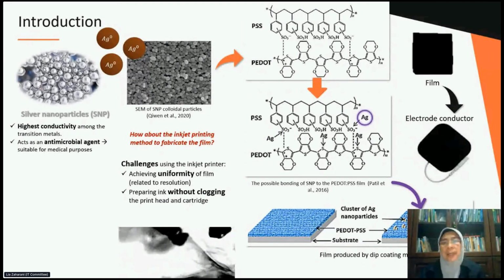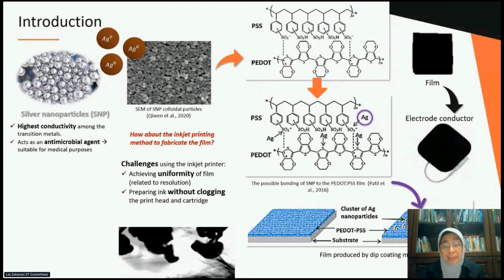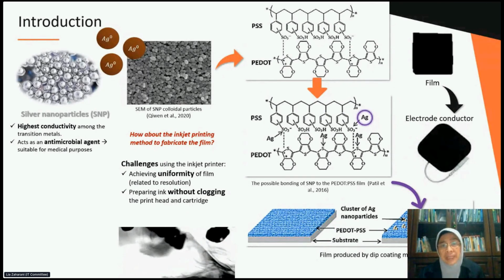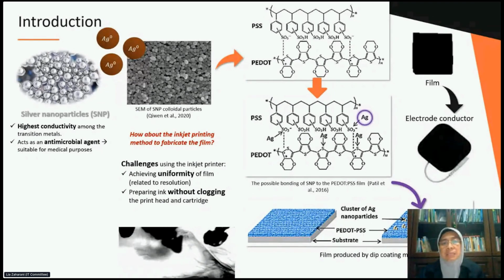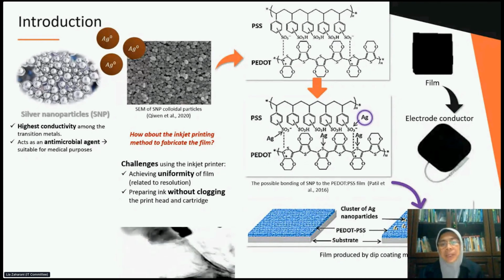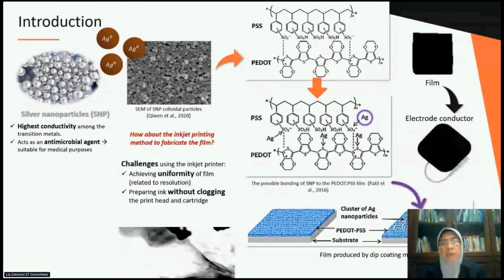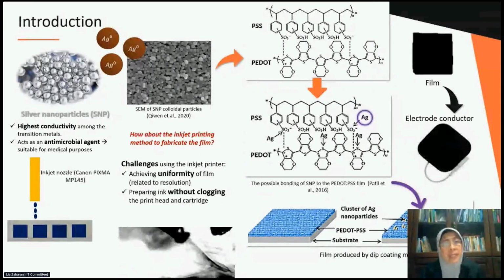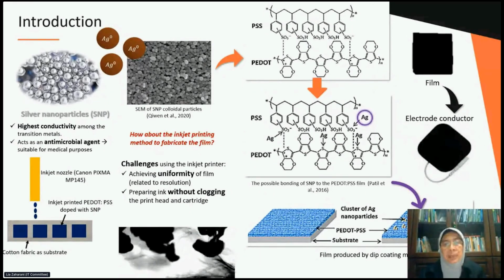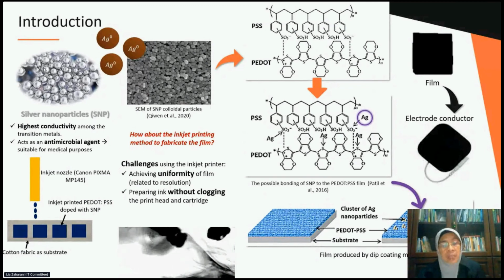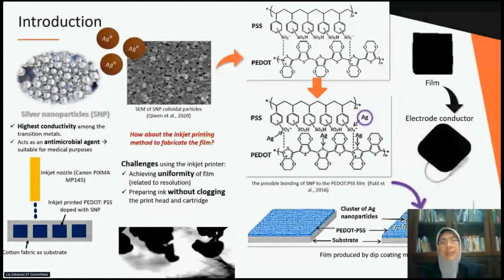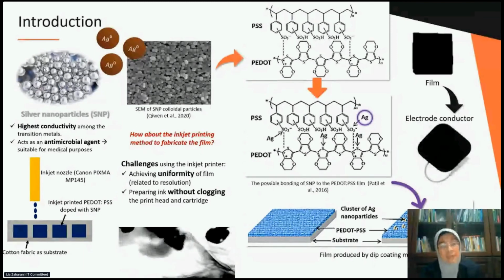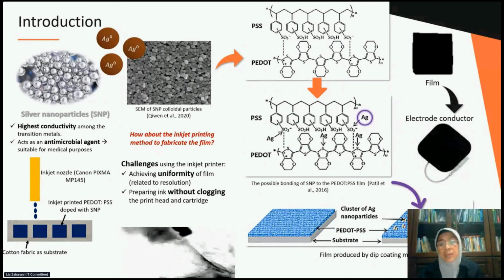So by employing an appropriate preparation method of the SNP, like sonication, and applying filtration before injecting the ink into the cartridge, the risk of agglomeration of the SNP should be minimized. Therefore, a uniform film based on PEDOT:PSS:SNP will be developed, and this is what our research is all about.